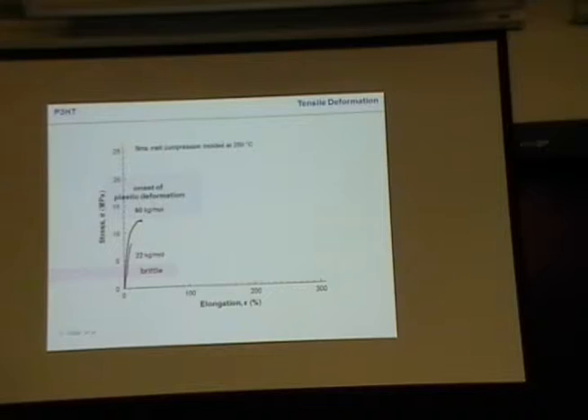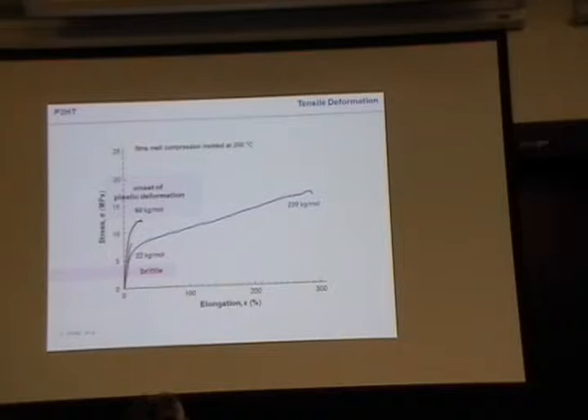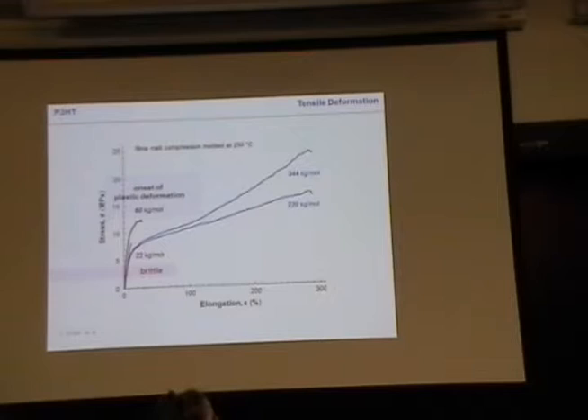Admittedly, it's not fully quantitative, but it gives you a very good feeling of where things occur. Because there are always some uncertainties about the molecular weights and how you measure them. If you go to very long molecular weights with a lot of those entanglements, between these entanglements you have a lot of chain to stretch — you can really have massive plastic deformation. If you go into high molecular weights, you see the material actually gets stronger while you stretch, so it deviates again. The material is being strengthened.